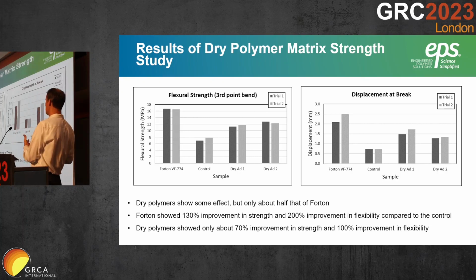In general, the dry polymers did have some effect. They did increase both the flexibility and the mortar strength compared to the control, with all the other parameters the same. But the Forton was much more effective: 130% improvement in strength and 200% improvement in flexibility compared to the control, whereas the dry polymers are about 70% and 100% improvement in flexibility. So there's definitely a difference.